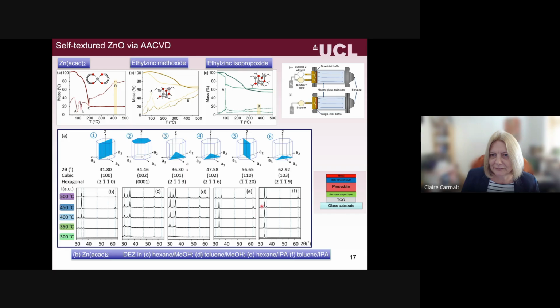And what this relates to is that you typically get this type of XRD for zinc oxide if you have an oxygen-rich environment around the zinc, whereas if it's oxygen poor, you tend to get this type of XRD formed. And so what we believe is happening is if you have the isopropanol, you form this complex in solution and it goes on to form this zinc oxide. With the methoxide, we don't believe it's forming this in solution, and so it's just reacting diethyl zinc with methanol, and so you get a different XRD coming out.